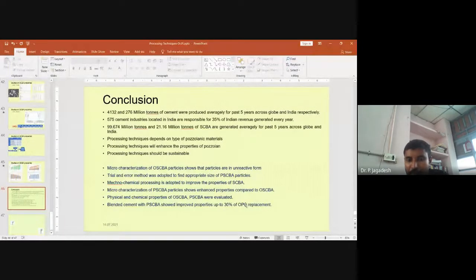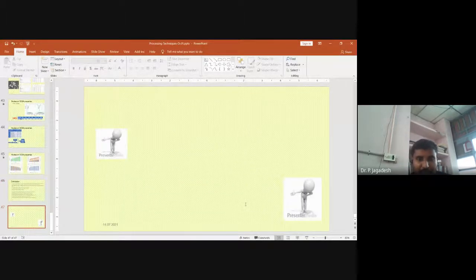On the conclusion of the sugarcane bagasse ash study: the micro characterization of original sugarcane bagasse ash particles shows that particles are in unreactive form. The trial and error method was adopted to find particle size. Mechanochemical processing is adopted to improve the property of sugarcane bagasse ash. Micro characterization of PSCBA particles shows enhanced properties compared to OSCBA. Physical and chemical properties of OSCBA and PSCBA were evaluated. Even blended cement of PSCBA showed improved properties up to 30% of OPC replacement. Hence, it is viable to introduce sugarcane bagasse ash as a replacement for cement.